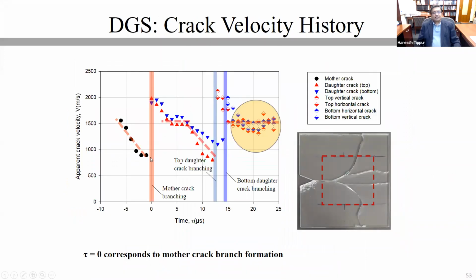You can plot the crack velocity histories, just like the way we did it in the previous experiments. The apparent crack velocity for the mother crack is already showing a slowing trend as it enters the region of interest. Notice that there is no gray line here where the crack had actually initiated originally in our earlier experiment. So we are missing the crack initiation, but we are only looking at mother crack propagation. Once the crack propagates some distance, while it is slowing down, it branches, produces two daughter cracks. You can see those daughter cracks are marked by the downward and upright triangles. These symbols begin to show a cruising velocity of about 1500 meters per second. And this 1500 meters per second, once again, begins to drop off when it is getting ready to branch again.